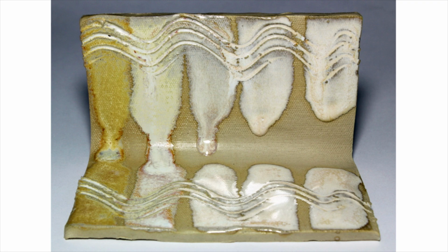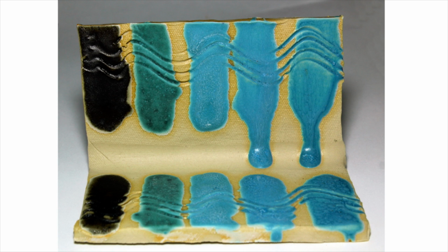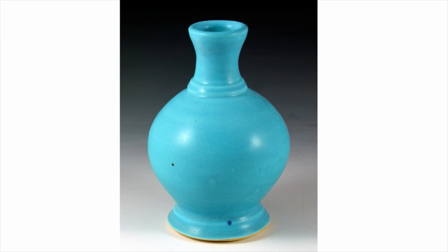Now, to lower or raise the melting temperature and control the flow of a matte glaze, take out all the dominant flux and then add it back in 5 to 10% increments. Note how increasing amounts of strontium carbonate lowers the melting temperature of the glaze and eventually causes it to flow uncontrollably. I chose the middle stripe with a 20% addition of strontium carbonate and added it to make this glaze for this bottle.